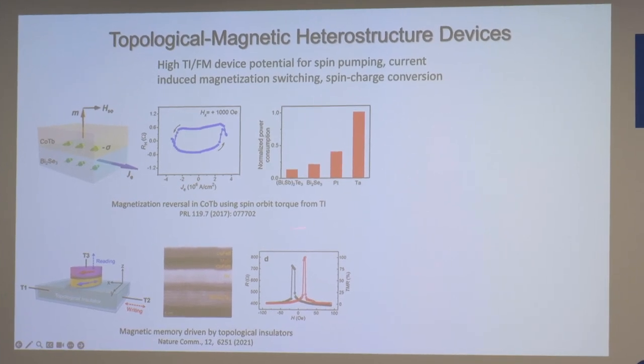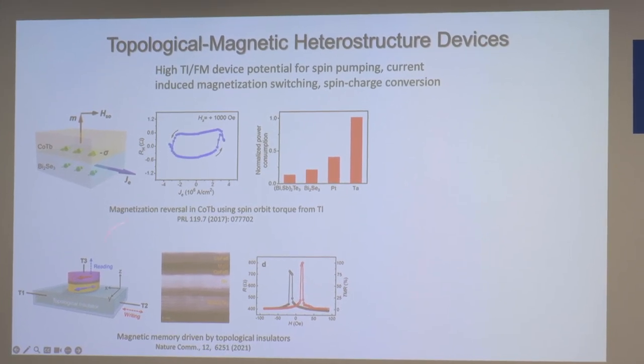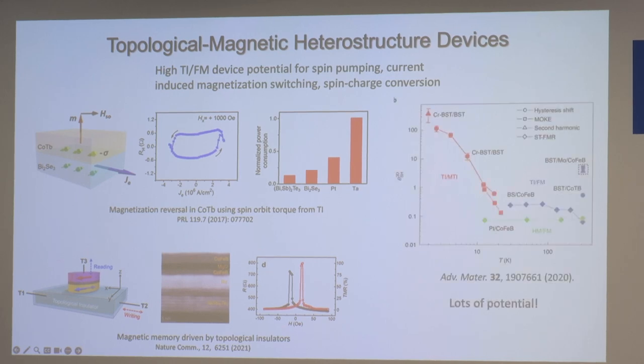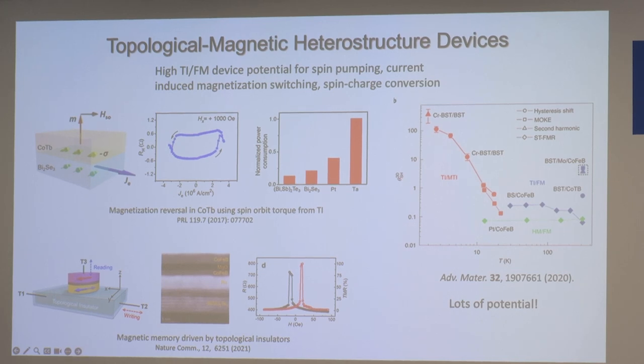And there's some controversy, again, about the mechanisms behind this, but this is just to show that people are now proceeding with trying to make these sort of devices. And in fact, you can see that if you measure the spin Hall ratio, which is just the ratio of the spin current to the charge current, you want that ratio to be high. These are the standard materials used in spin torque devices. And these are the topological materials. Even at room temperature, they are much better than any of the standard materials out there. And this is because of the spin momentum locking on the surface.